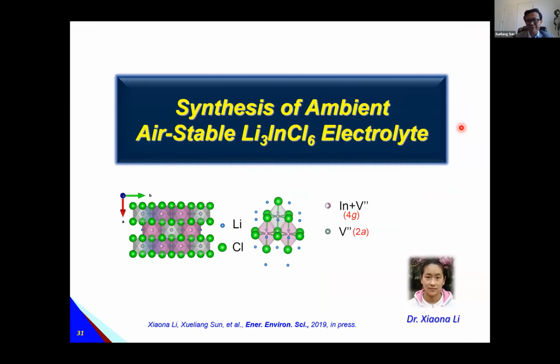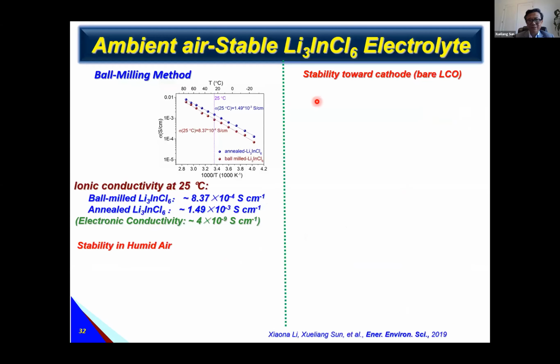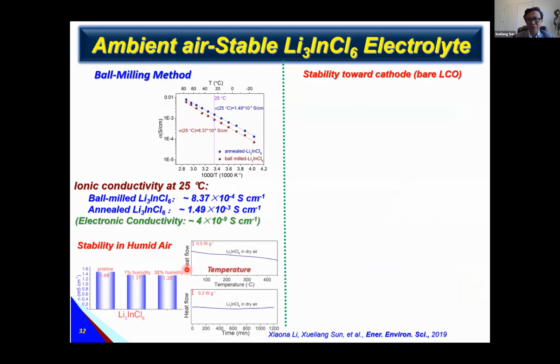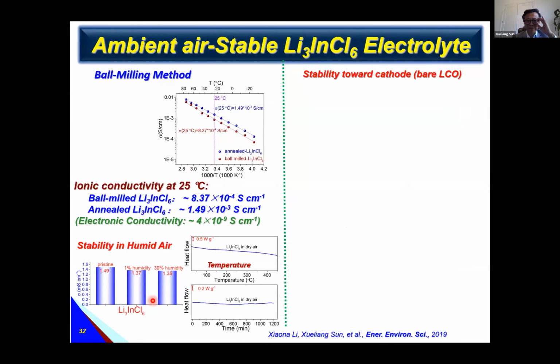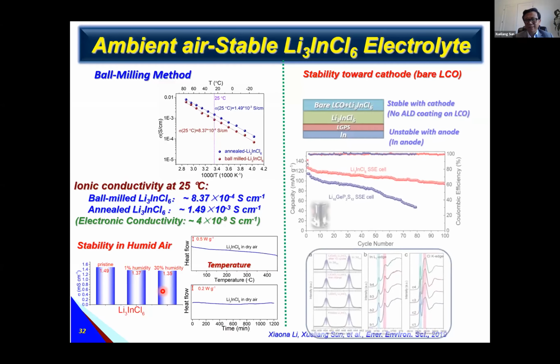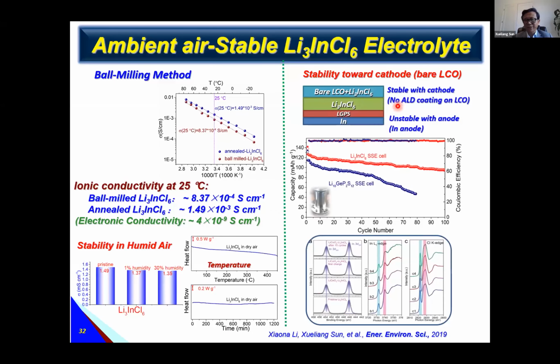So let me give you one example in this system. Actually, in the beginning, we wanted to synthesize a stable lithium indium chloride. So we used the ball milling method. After annealing, we found this system can get 10⁻³. Not only in dry air and dry oxygen, we found it is also stable in humid environments. For example, at different humidity it maintains good ionic conductivity, and it is also very stable with the cathode.